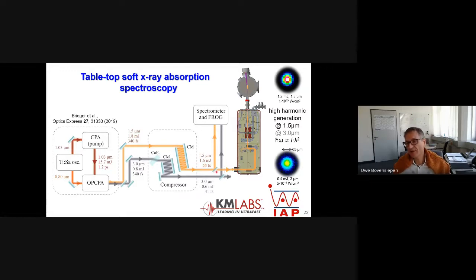And this light we now couple into a hollow core capillary. And here we collaborate with KM Labs, Colorado, and the spectrometer we get from Berlin, IAP. And we then couple this light to a really small diameter. So here you see the focusing, the transmission through 100 micrometer fiber after focusing to 65 micrometer. And then here we bring in the helium gas at rather high pressure, and we analyze the generated harmonics spectrum.